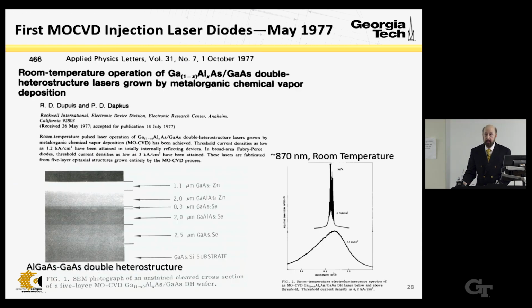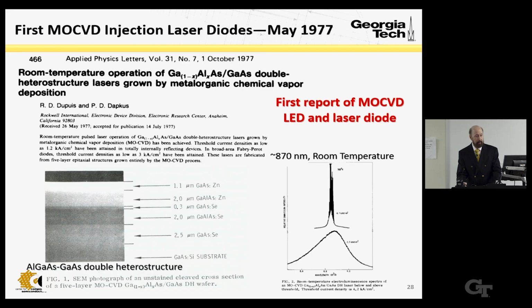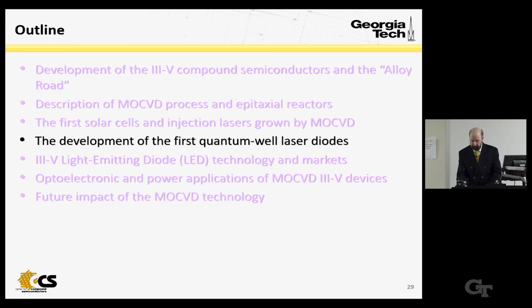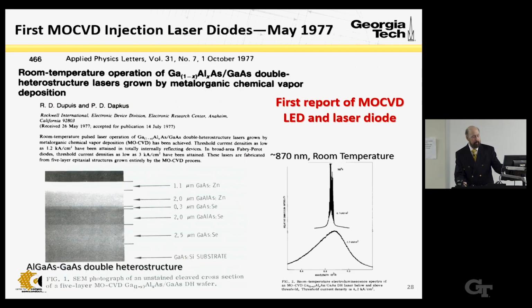Let me turn now to the light emitters. The first injection lasers, as I mentioned, were 1962. They were diffused junction, homojunction gallium arsenide devices. AlGaAs lasers appeared around 1969 and 70. In 1977, we published the first MOCVD grown laser diodes. They were aluminum gallium arsenide double heterojunctions. You see in the SEM picture there on the left-hand side, and on the right, the spectrum. These were room temperature pulsed lasers. So they weren't low temperature like the first gallium arsenide lasers.